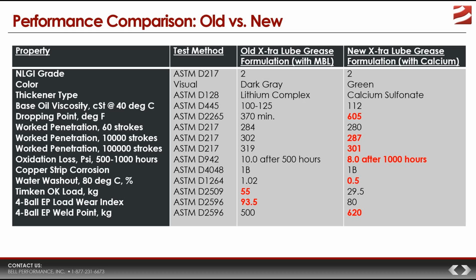That's why you see oxidation loss, PSI 500 to 1,000 hours. What happens is that if the grease reacts with the oxygen, it's going to use some of that oxygen up over the course of the oxidation reactions taking place. And when that oxygen gets used up, it causes the pressure to go down because there's now less oxygen in that chamber, since some of it has reacted with the grease.